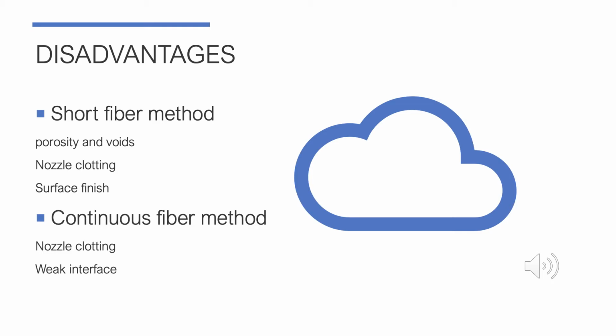FFF, however, suffers from limitations like porosity and voids. Voids have been observed to form in between the extruded filaments, thus leading to delamination and reduced tensile strength. Reinforcement is also more effective along the direction of the filament as compared to the across-the-layer direction, as fibers tend to lie along the extrusion direction, resulting in high anisotropy in mechanical properties.